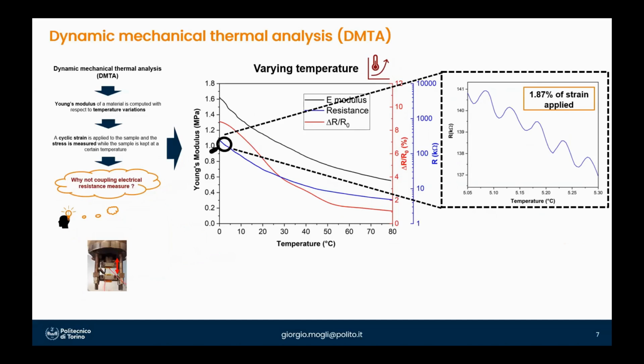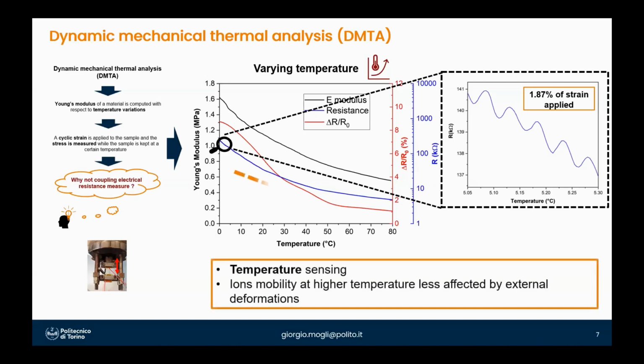And moreover, the relative variation of resistance with respect to each cycle was computed and is reported in the red line. And as we can see, it decreased when temperature increased, since the ionic mobility at higher temperature is less affected by external strain. So the sensors are less sensitive to external deformations.